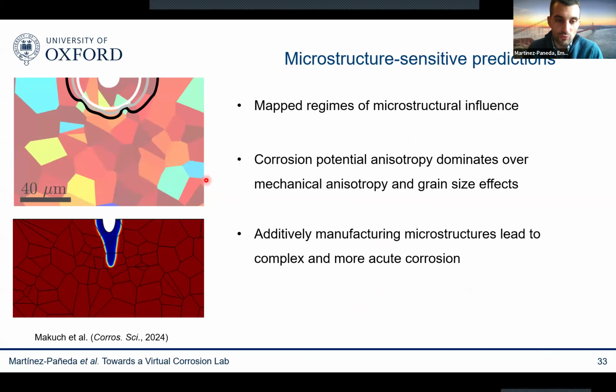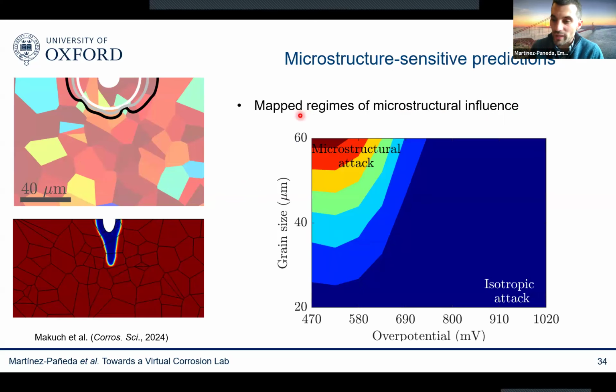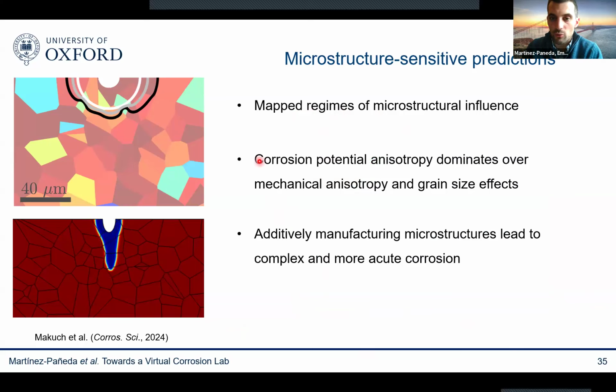And we have ourselves tried to focus on these three aspects here. So first, we wanted to map regimes of microstructural influence. So we can run simulations with different combinations of overpotentials and grain sizes, and we can build maps like this, where we have some measure of overpotential of the environment and grain size, and we can map over which regimes we can handle well with an isotropic model, and over which regimes we need to resolve the microstructure of the problem. We've also learned that corrosion potential anisotropy dominates over mechanical anisotropy and grain size effects, and we can also use this to understand why 3D printed materials are more susceptible to corrosion due to the influence that the microstructure plays in this corrosion process.